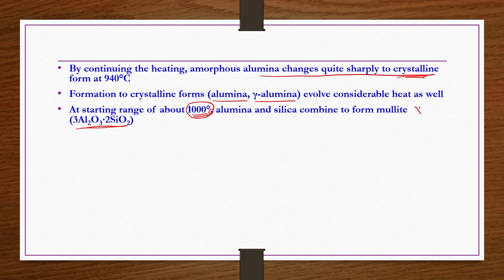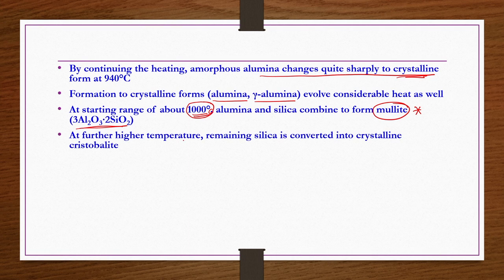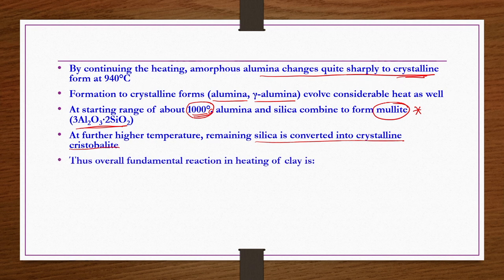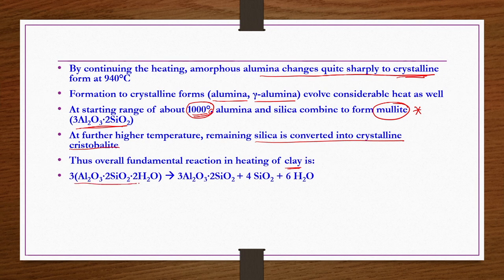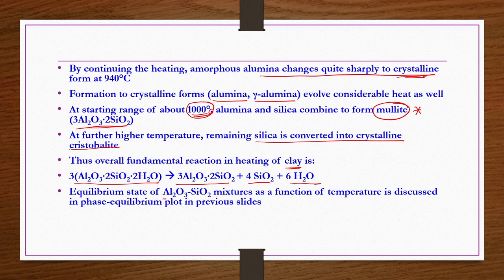Okay, so this is very essential. This is one of the best refractories that is available. At further higher temperature, remaining silica is converted into crystalline cristobalite. Cristobalite is nothing but crystalline silica. So, thus the overall fundamental reaction in heating of clay is this one. If you react 3 moles of kaolinite, you get 1 mole of mullite and then 4 moles of silica and 6 moles of water vapor. Okay. Equilibrium state of alumina and silica mixtures as a function of temperature is discussed in the phase diagram anyway.